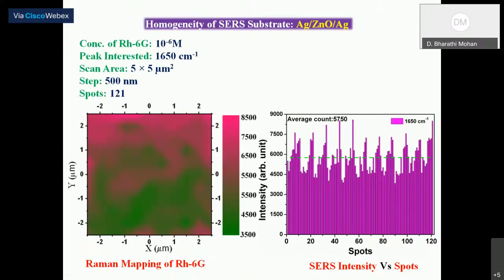The homogeneity of the SERS substrate has been tested using Raman mapping. The concentration of rhodamine 6G is 10 to the power minus 6 molar. The peak in which we are interested is 1650 centimeter inverse. The homogeneity of the adsorption of the biomolecules is very, very important when it comes to the sensitivity of the SERS substrate. So the homogeneity is studied using rhodamine 6G molecules on our SERS substrate, and this picture shows a very good homogeneity of the SERS substrate.